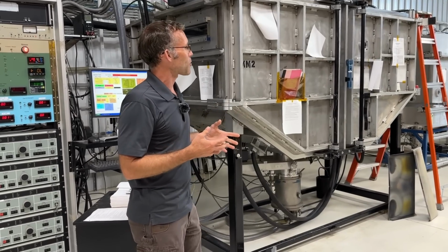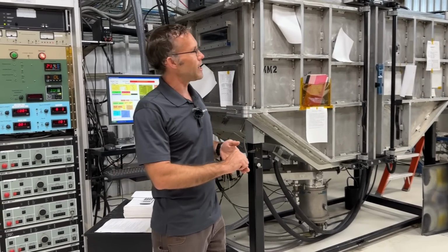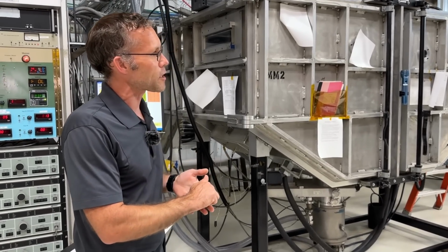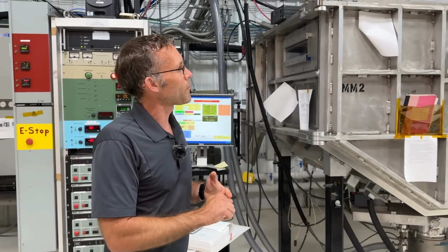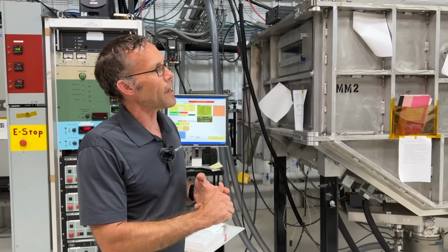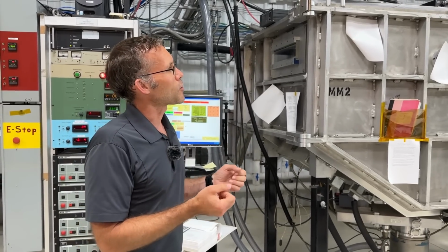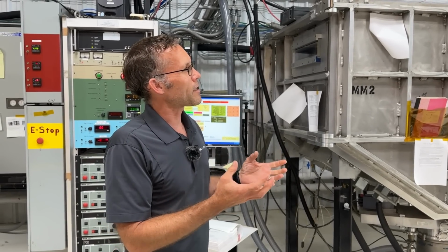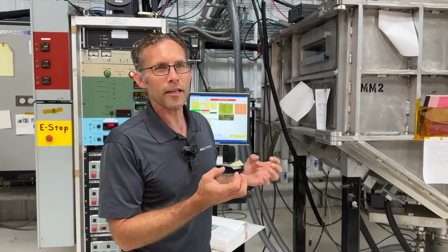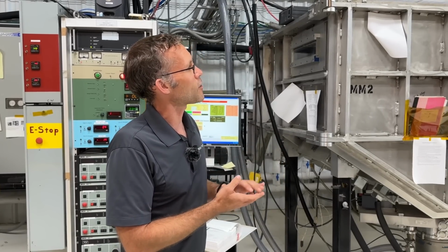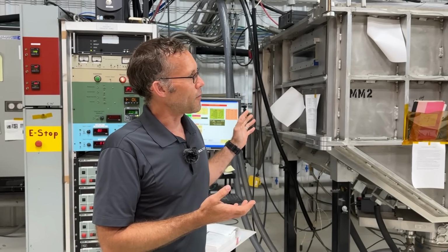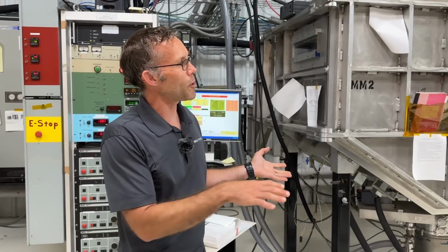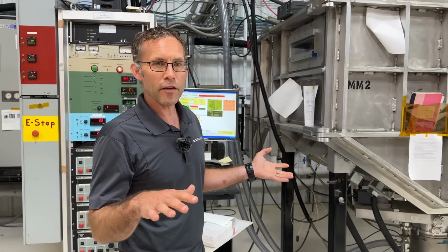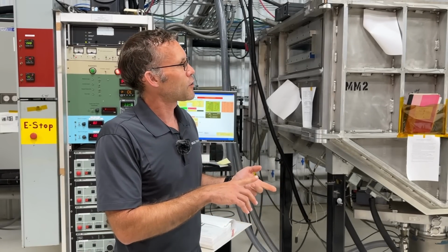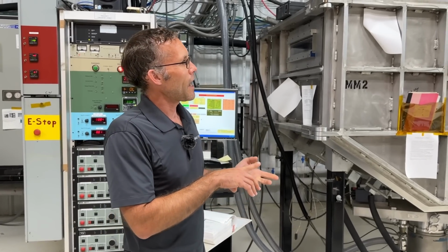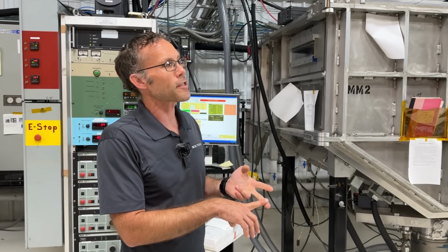They do that with a sputtering process. We use stainless steel as an adhesion layer to the plastic first. Then we use a stack of aluminum, and the aluminum is put down in such a way that it creates a texture. We don't want a smooth, mirror-like aluminum, because that makes it really difficult for the amorphous silicon to stick to it. We need a little bit of texture to help it stick. So we put down a layer of stainless, which helps the aluminum adhere to the polyimide. Then we put down a layer of textured aluminum, which gives us the conductivity we need to get the power out of the device in the end, and also gives us the texture we need to make sure the amorphous silicon sticks.